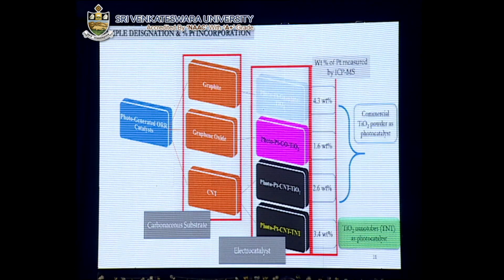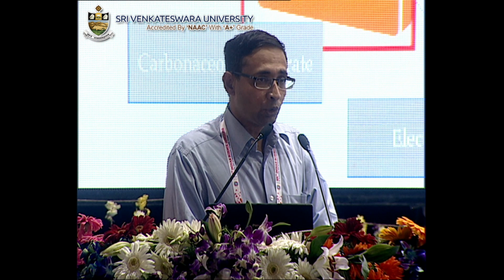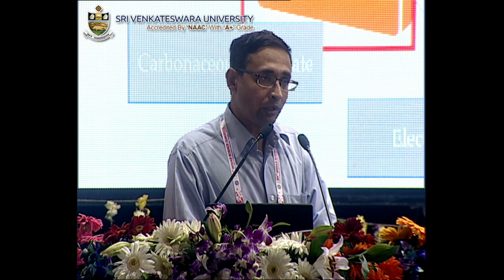And we have here a sufficient number of samples which we made in our lab, and all of these are made with three different carbon substrates. One is graphite, another is graphene oxide, and the third one is carbon nanotubes, CNTs. And in the case of TiO2, we used the TiO2 particulate form as well as the TiO2 nanotube form, because TiO2 nanotubes as such have a larger surface area, like CNTs.